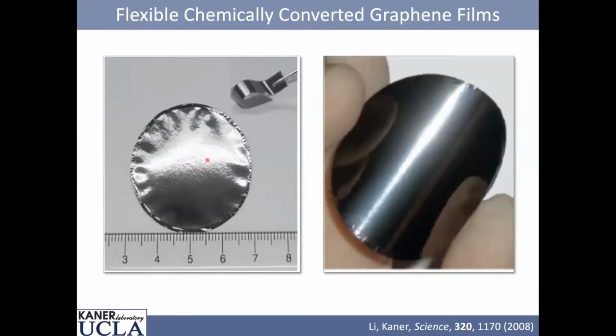Now you may say, well, how does that differ from graphite? Because graphite is just stacks of carbon. But graphite's actually three-dimensionally ordered. It has an AB-AB stacking. This has totally random stacking. So we just take thousands of sheets and stack them together, reforming van der Waals interactions. And you can see this stuff's pretty strong. And you can see how smooth it is. You can see reflection in it.